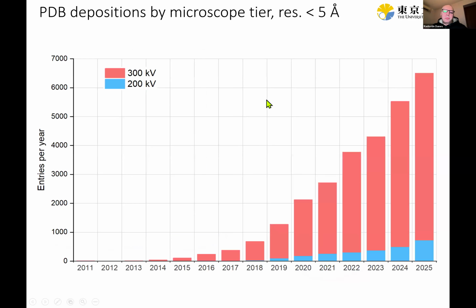Now, if you look at the depositions by the two types of microscopes, here you see 300 versus 200, there is a big discrepancy. So it's roughly 1:9 or 1:10 in terms of number of depositions. And this ratio hasn't changed much, apart from the last couple of years where it seems that 200 kV machines are starting to gain more ground. But in general, judging by the depositions, it's 1:10, which is quite surprising when I saw that.